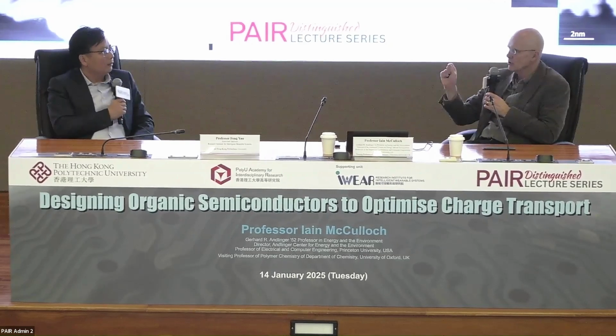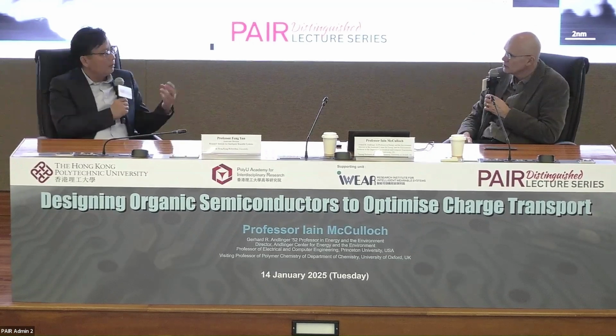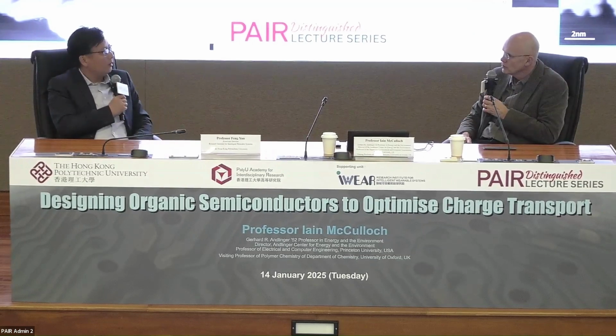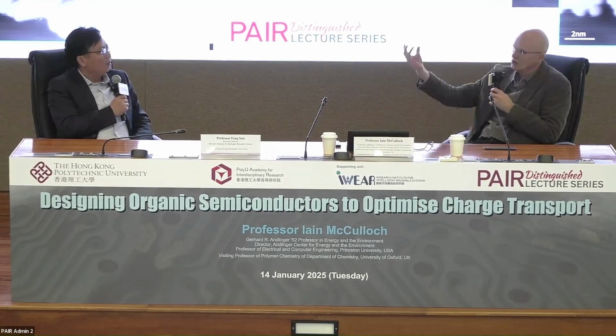When you introduce more aliphatic component, then you reduce the swelling. Please, what is the influence on the mobility or carrier transport for the material if we have a different level of swelling? So I think that high degrees of swelling lead to disruption in percolation, increase in disorder, and reduced carrier mobility. I think there's a lot of trade-offs, but you need a certain level of hydration in order to facilitate the ions coming in, at least a little.